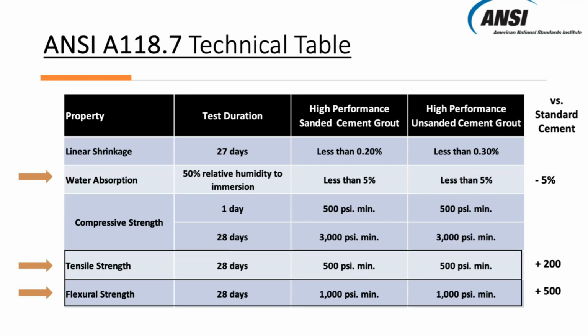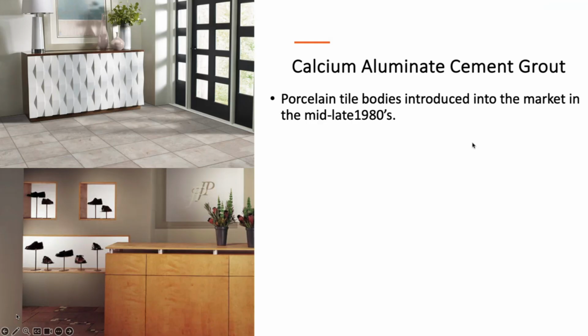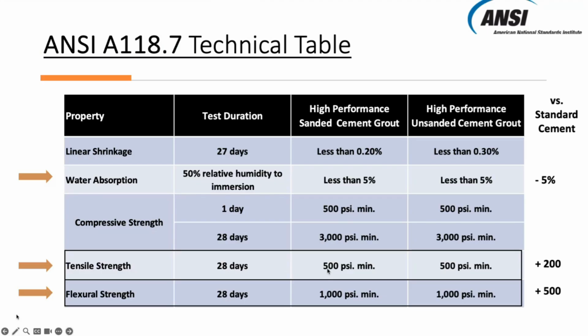So when you look at the ANSI A118.7 technical table, the tensile strength on that, when you are looking at that versus the standard, you're going to have 28 days, 500 PSI minimum, and you're going to have flexural strength after 28 days. And the reason why we do 28 days, because that is a full cure for a cement-based product, whether it's concrete out in front of your house, whether that's thin set for setting the tile, whether that's grout, anything that is cement-based, 28 days is a full cure. So you're going to have 1,000 PSI minimum on that.